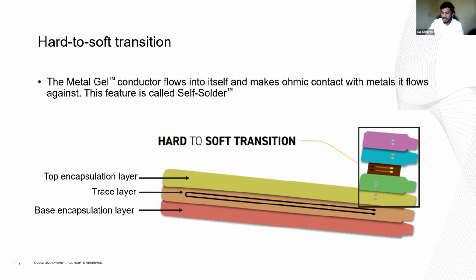gel. The internal structure of metal gel provides enough stability that you can directly bond components to the metal gel trace without concerns of losing contact or shorting circuits. This increased mechanical strength of the metal gel also enables patterning of multi-layer circuitry with deformable VIA structures directly connecting individual planar layers. And essentially, you can do traditional PCB structures, building on a thin sheet of plastic film.